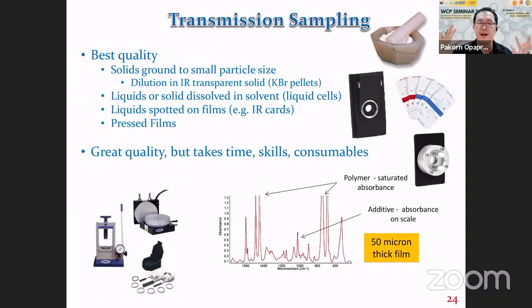We can also make a sample by mixing it with KBr powder and compressing it into a pellet, and then measure the spectrum. We can make standalone films, but they need to be very thin. If you have a thick film, your signal may not be of high quality, especially for quantitative analysis. We also have a liquid cell. You can put your sample in liquid form into the cell and then measure spectra in transmission mode. So these are all the possibilities we have to measure samples in transmission mode.